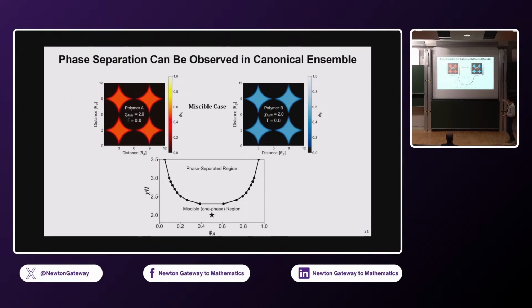All right, so this is the typical polymer phase diagram, and we're looking at a symmetric system here. So we take polymer A and B, and a key point here is that those two polymers have neutral interactions with the particle, meaning the particle does not favor one over the other. They have the same strength of interactions. If we put the polymer blend where they're supposed to be well mixed and run this simulation, you'll see that A and B both distribute homogeneously in these four interstitial pores. If we go up in chi N and put this in a region where you expect polymer separation, that's what you see: a region that is rich in component A, and also rich in component B, meaning that there is phase separation.